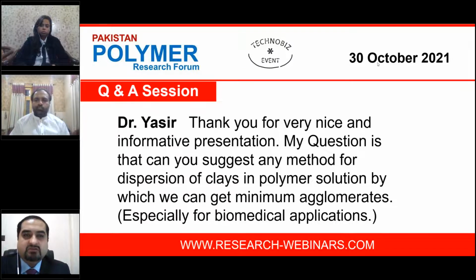So my suggestion would be to try to use ultrasonication or exposure to microwaves, and then make sure that you eliminate whatever solvent you are using or moisture as quickly as possible by centrifugation, or there are other rapid drying techniques available, as a result of which you can eliminate most of the moisture or solvent very quickly.